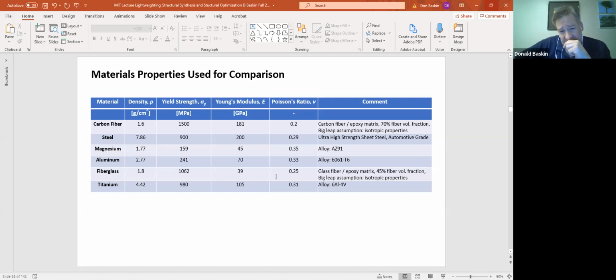Fiberglass, like any composite, can have very different values depending on how much fiber you're able to incorporate together. But assuming an average fiberglass with a fiber volume fraction of about 45%, the density would be about 1.8, so about that of magnesium, so pretty low. The yield strength would be not too bad, about a gigapascal. The Young's modulus is actually very low because the glass fiber just isn't that stiff, and the epoxy matrix is not very stiff either, so it's only about 39 gigapascals.